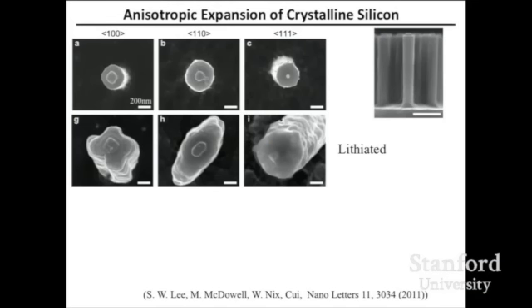The 100 becomes a cross shape. The 110 becomes an ellipse shape. The 111 becomes round, or more or less a hexagon shape. The expansion is highly anisotropic. This has implications for your battery design. If you put silicon together, depending on the orientation of the crystal structure, the expansion in different directions is different. So you need to think about that when designing your battery's electrode.